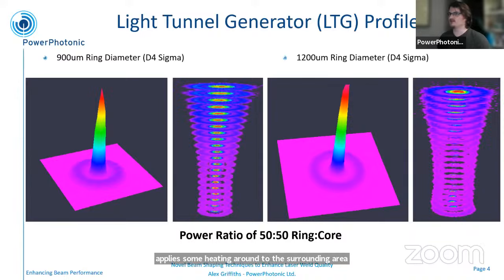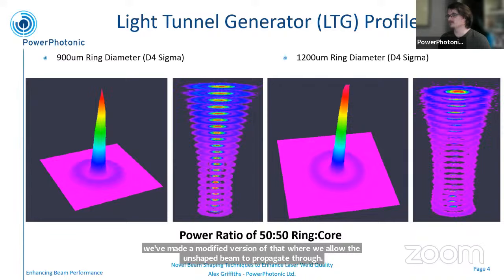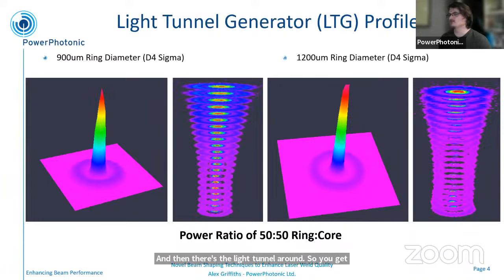What we have with the light tunnel generator is we can generate a light tunnel where this ring profile propagates through focus. So we've made a modified version of that where we allow the unshaped beam to propagate through, and then there's the light tunnel around it. So you get this core and ring geometry of your spot shape, but it also propagates like that for quite a significant distance. So the depth of focus is improved.